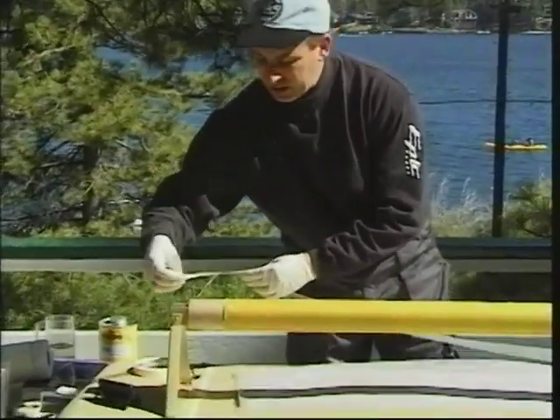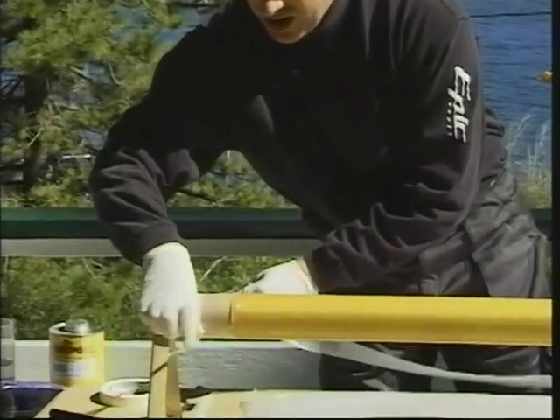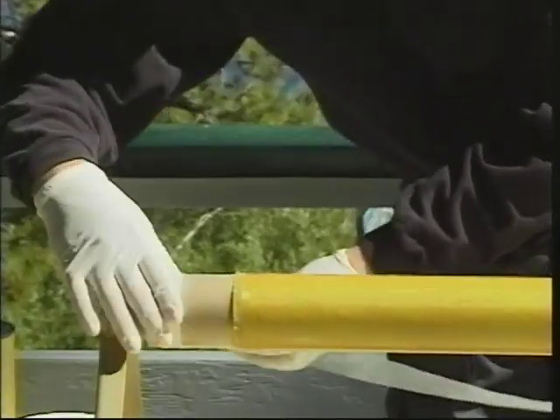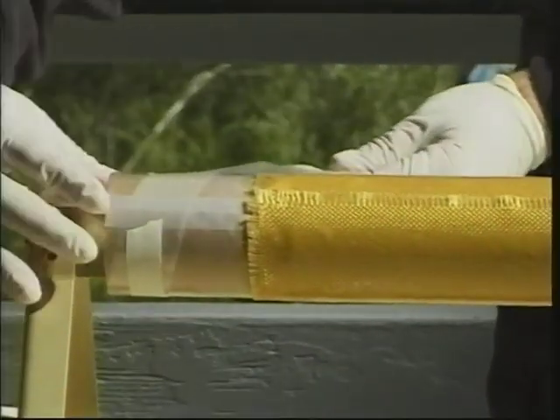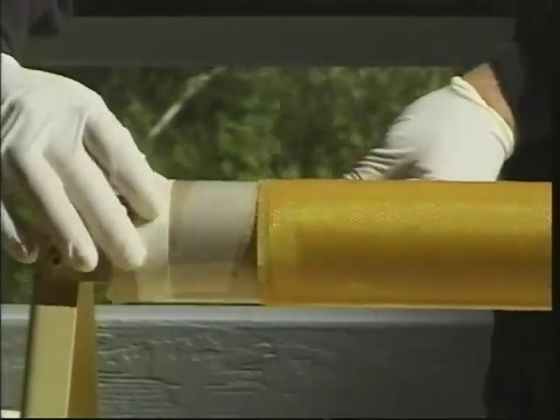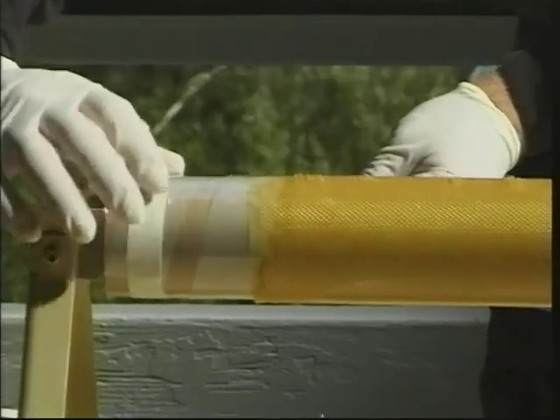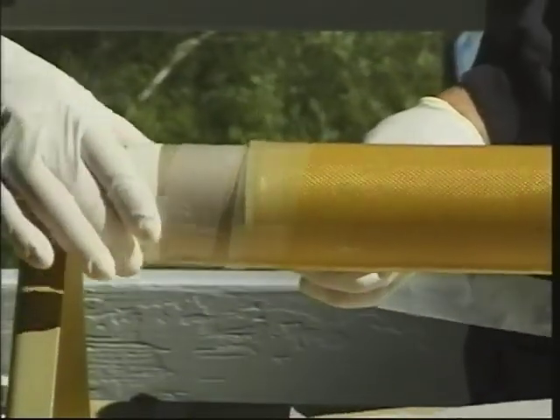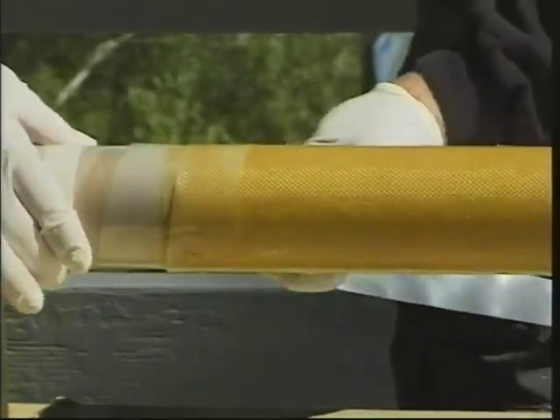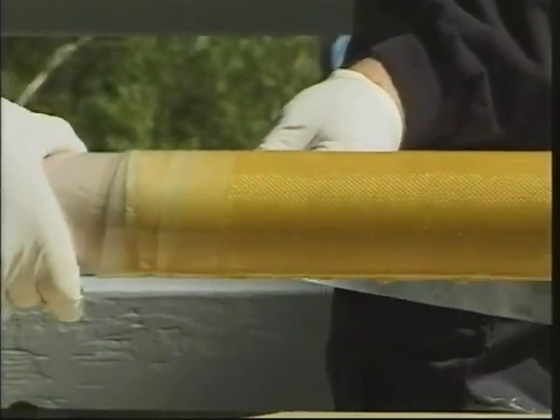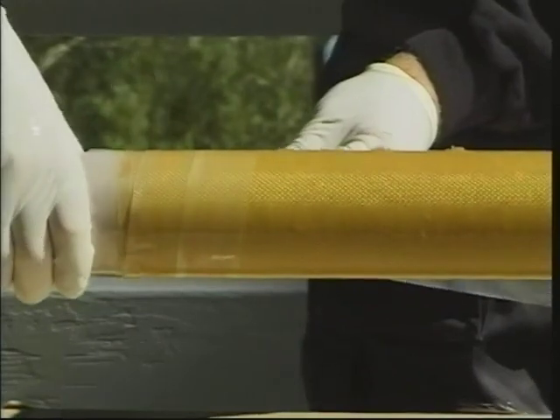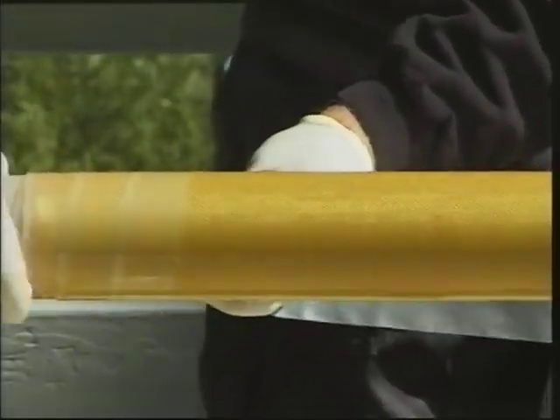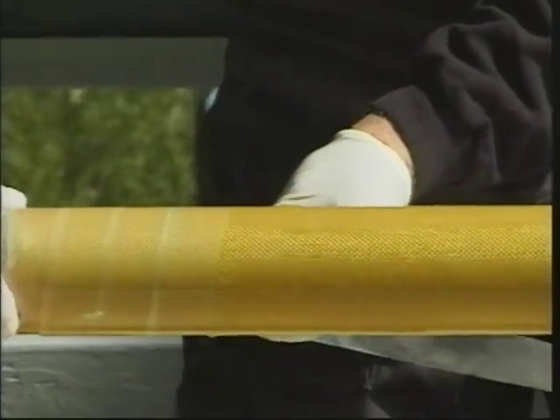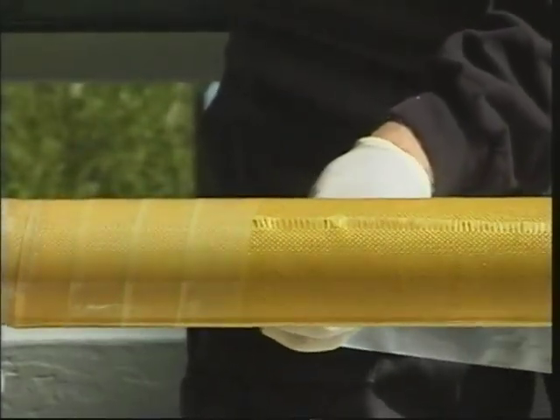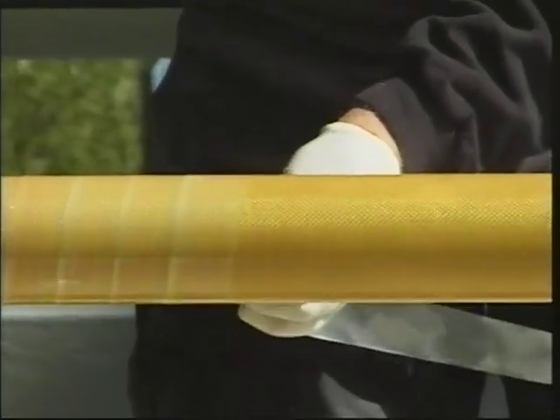So give it a little piece of masking tape on the end. Start the shallow angle. Make sure that masking tape's fixed down well. And look, I'm wrapping in the same direction that the Kevlar went onto the tube. By doing this, I'm tightening down that Kevlar in its wrap. If you go against how the material is wrapped onto the tube, you're going to probably incur some wrinkles and bubbles on the inside of the laminate. So go in the same direction that you wrap the cloth on.